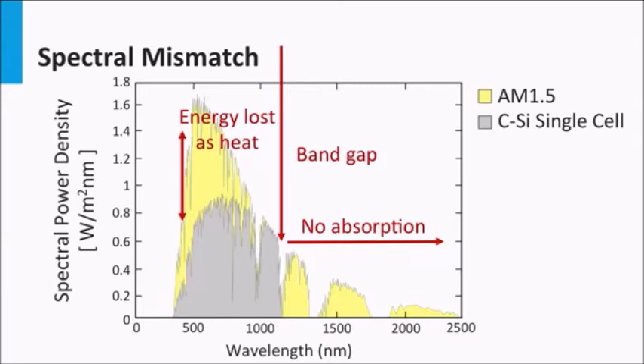All energy present in the solar spectrum below the band gap is not absorbed and can be considered as an optical loss as well. Both loss processes, heating and non-absorption, depend on the band gap. The higher the band gap, the smaller the losses due to heat, but the larger the energy losses below the band gap. The smaller the band gap, the larger the losses due to heat, whereas the energy losses below the band gap decrease. This suggests that if we only consider the optical losses and ignore all other losses, we will have an optimum.